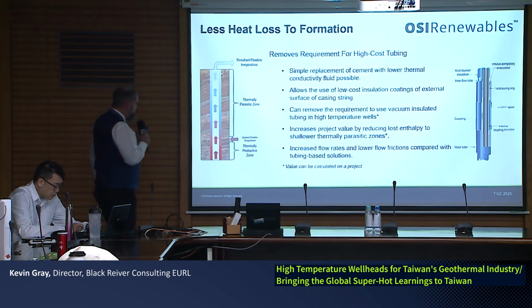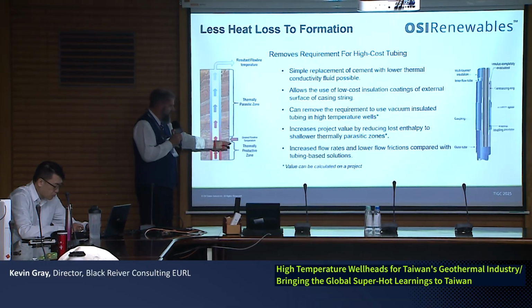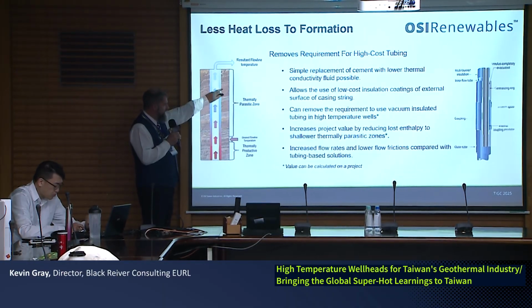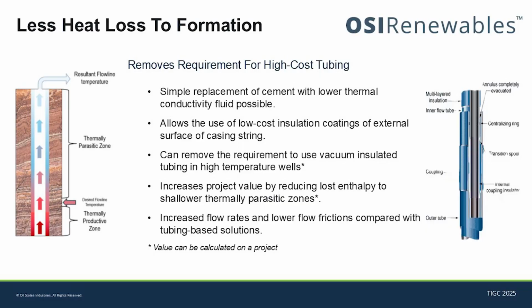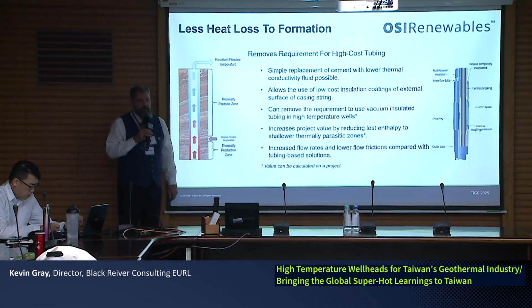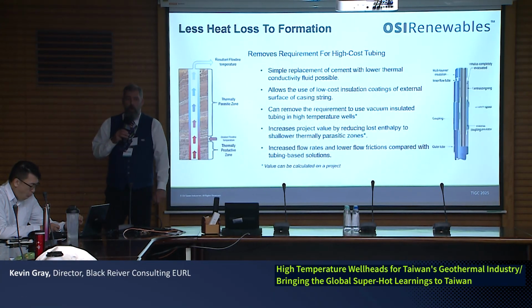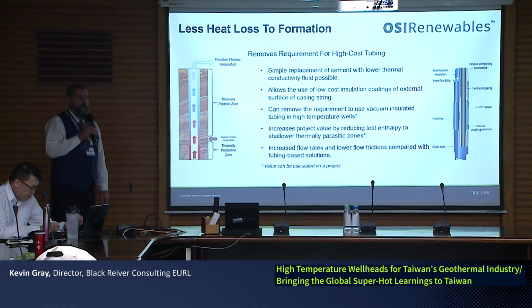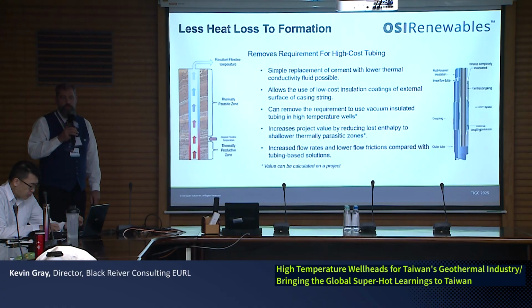So what we typically have is a thermally productive zone down here. That's the desired temperature we want. So anytime our flow is in rock that's lower temperature than our desired temperature, that rock is thermally parasitic. It is stealing our money. All of this rock is stealing money off our project. So what we want is as low a thermal conductivity to the formation as possible. And because we've got an open annulus, we can run a very simple low-cost foam insulation or sleeve on our casing string, and that will reduce the loss of temperature to surface.